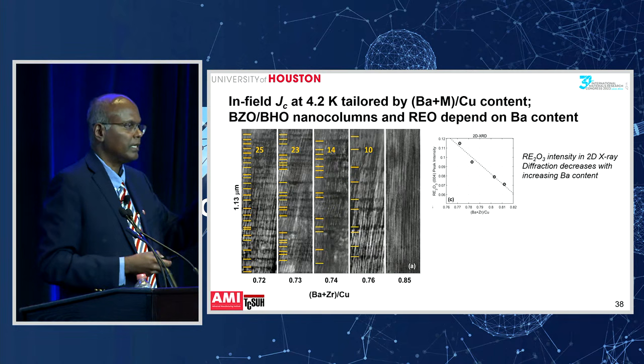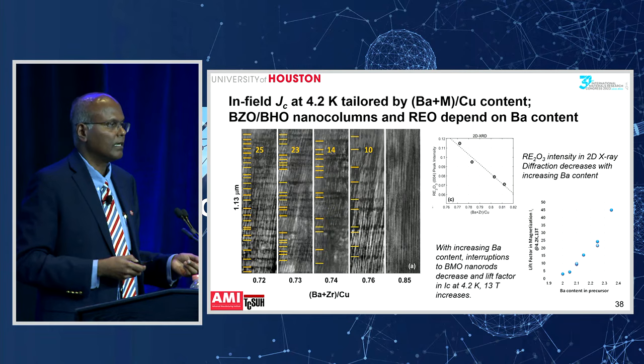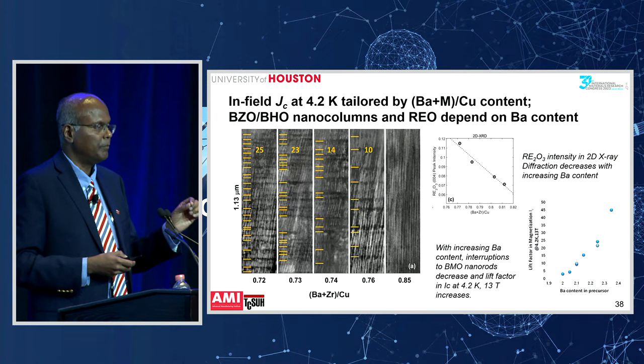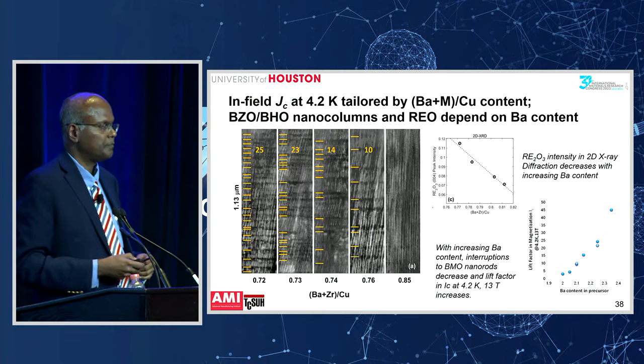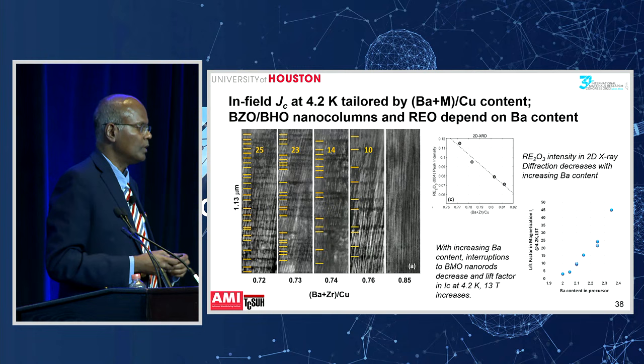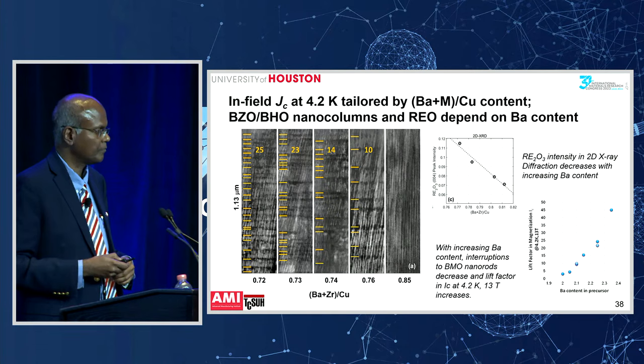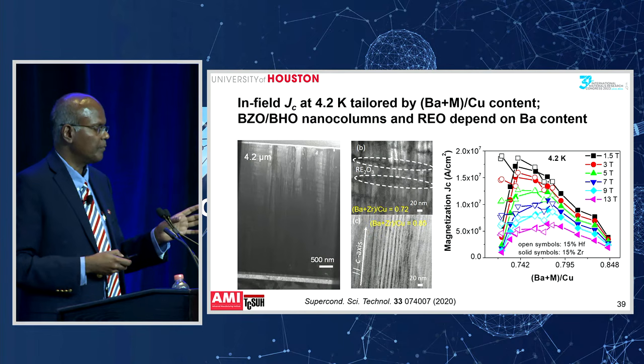And consequently, the pinning capacity, what I'm showing on the chart on the bottom, the pinning ability of the film, actually keeps increasing quite drastically as I increase the barium content. So that is a method that we found is quite effective to improve the pinning centers and also to increase the critical current density. You can see that in the chart on the right-hand side. As you increase the barium content in the film, you can see there's actually a peak performance.